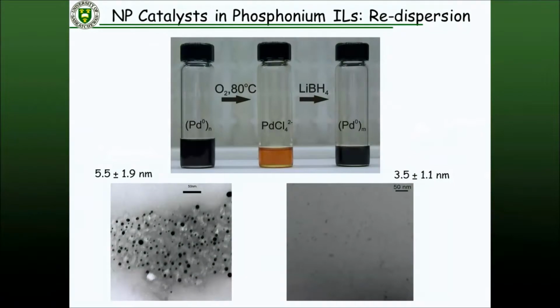But we're in a halide ionic liquid, right? We have a huge concentration of halides in there. All you need to do is open it up and heat it in air at 80 degrees Celsius. After an hour or so, you've got complete oxidation of the palladium back to the palladium chloride salt. Re-add a very small amount of the initial reducing agent, and we get back to a palladium nanoparticle system, but with smaller particle sizes than we originally started with. Right?